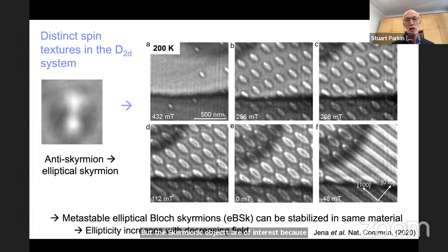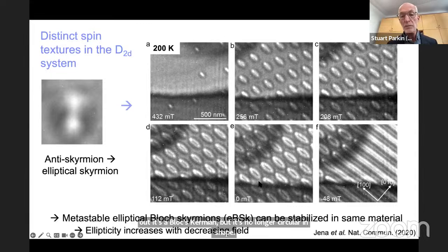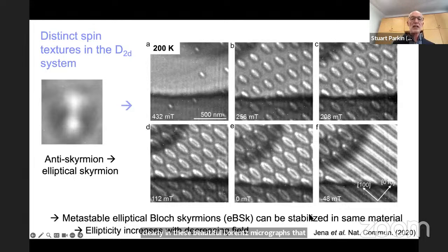There's some topological charge associated with them that's believed to prevent them from evolving from one structure into another. However, what Jagannath found was in the same material, depending upon the temperature, you could achieve a totally different structure which had never been seen before. And it turns out it's a Bloch skyrmion, but it's no longer circular in shape. It has this elliptical shape that you can see very, very clearly in these beautiful Lorentz micrographs that Jagannath took. And here you can see again how they evolve in magnetic field.